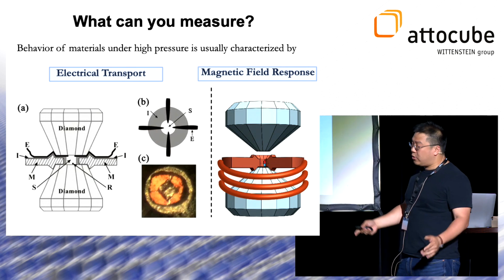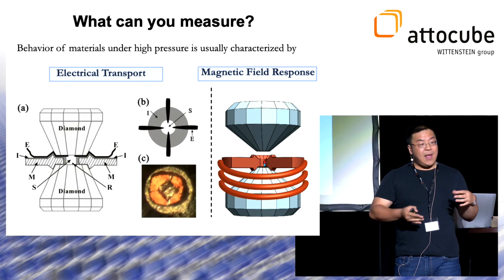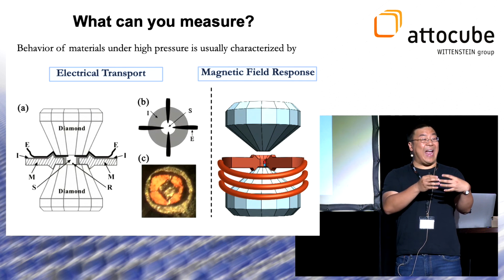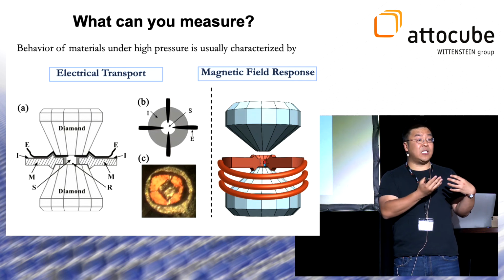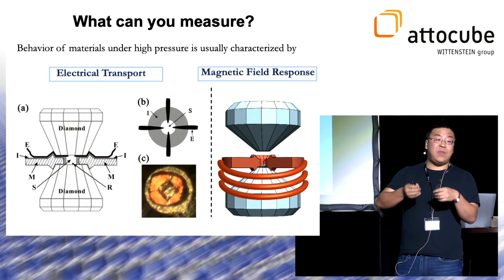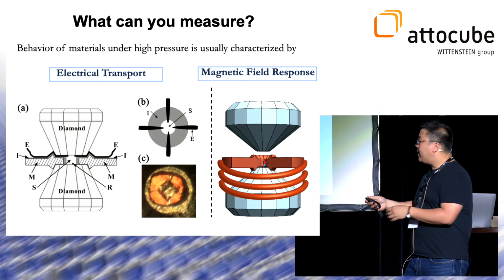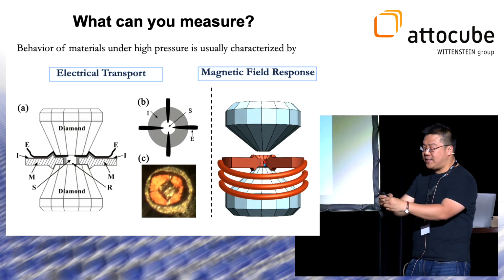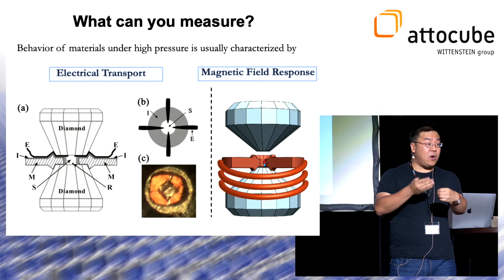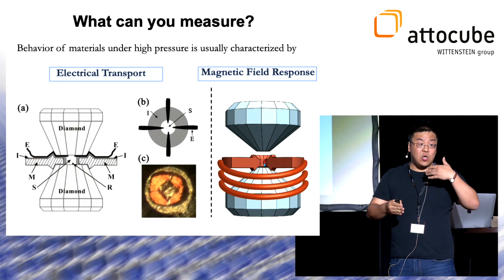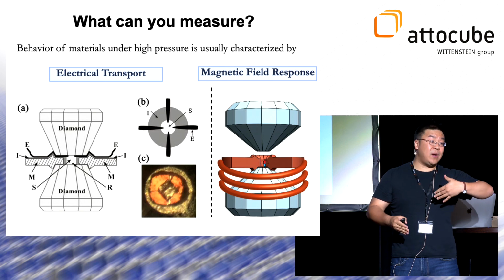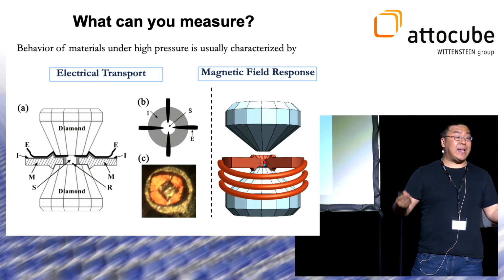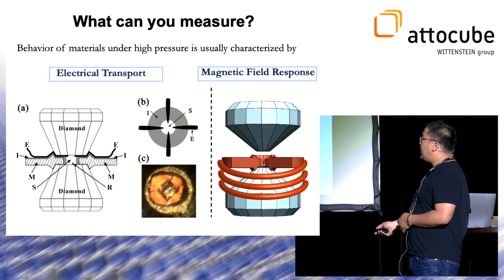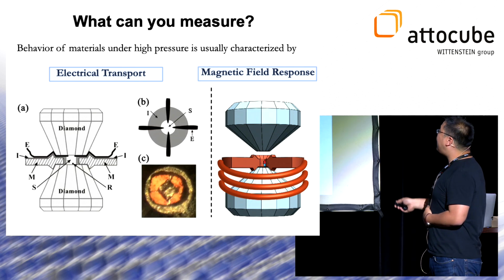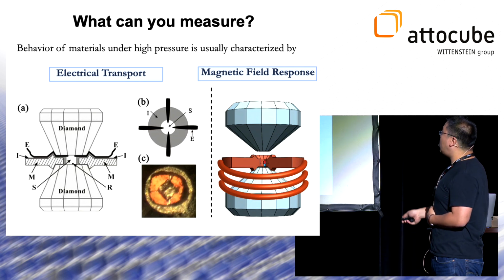And so electrical transport needs no introduction. I can just tell you that the way you do magnetic measurements for these diamond anvil cell experiments is also super simple. You think about a pickup coil design. So you imagine having a solenoid that applies a little bit of an AC current that applies a magnetic field, and then you lock into that response and try to measure in a pickup coil the changing magnetic response of your system.